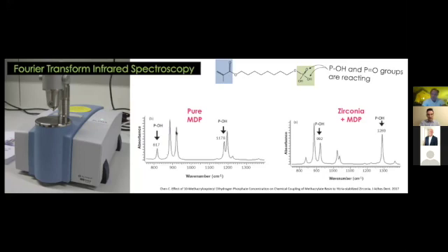which wavelength of infrared light made them vibrate, I think. And then they mixed the MDP with zirconia, and they did the FTIR again, and they found that these bonds here change in activity when you combine MDP with zirconia. And so that was evidence that this OH group and this double bond O group here are active when you add MDP and zirconia together. So I guess that's neat.